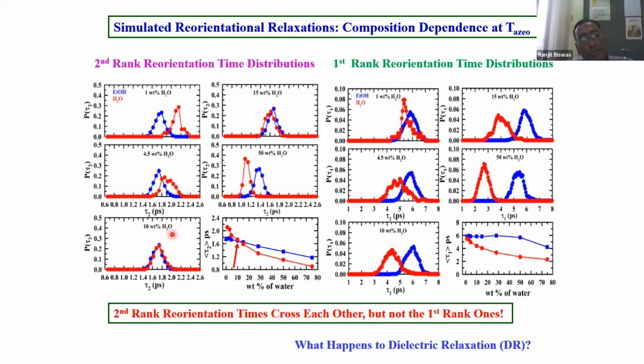And this is understandable, as we know that the rotational friction or rotational diffusion coefficient is averaged out in a manner somewhat different from the averaging out of the translational diffusion coefficients. But here one thing is interesting: the diffusion coefficients are actually crossing each other. And you see tau_2, which is the inverse of the diffusion coefficient, in this range: viscosity is increasing, but reorientation time is decreasing. So this is a decoupling.